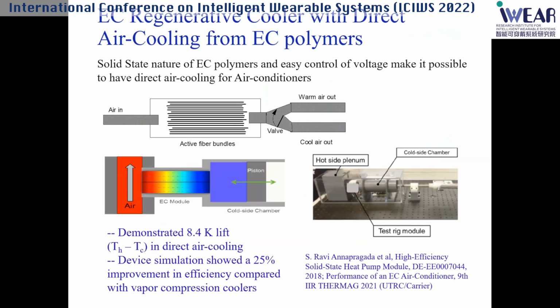United Technology, a company in the United States, and also Carrier, which is a major HVAC company that produces air conditioners and refrigerators in the United States, did a study using EC polymer. In this case, they basically put EC polymer film in a stack and directly used air to exchange the heat and generate a regenerative cooling cycle. This is the device configuration - hot side, cold side, and here is the EC chamber. They made a device with a temperature lift of about 8.4 Kelvin. They also carried out a simulation which shows that with high EC performance, for example if delta T can be 7 or 8 Kelvin, the EC cooling device can have a 25% improvement in efficiency compared with the vapor compression cooler. Those are very encouraging results.